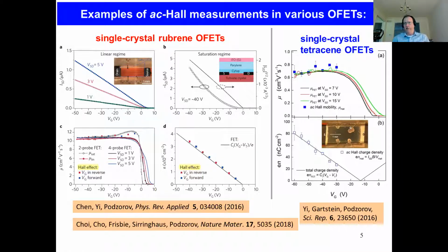And this was initially a surprise, one of the mysteries of the Hall effect, that we actually see apparently a fully coherent Hall effect here. You can see that Hall mobility matches the longitudinal mobility, and carrier densities are matching too. The reason this was a mystery is because it was believed that when the mobility is below 1, the system should not be exhibiting band-like transport at all. It should be a hopping system. Nevertheless, we see a fully coherent Hall effect.